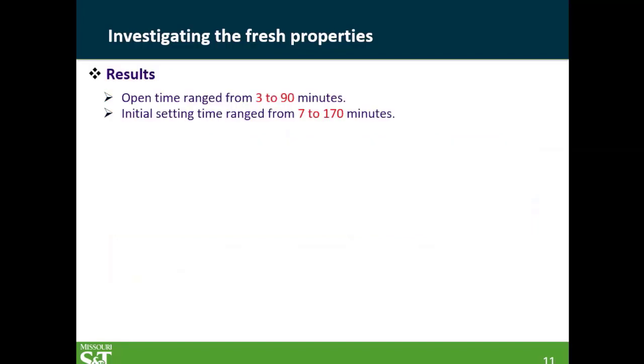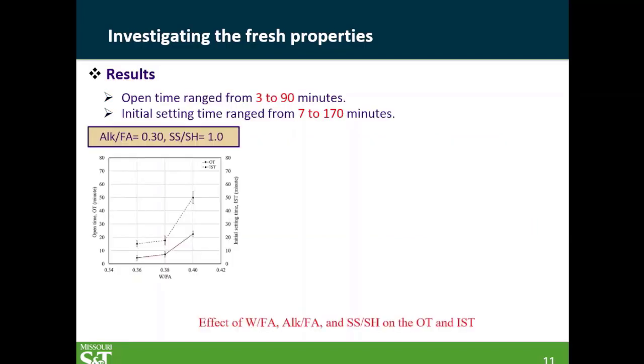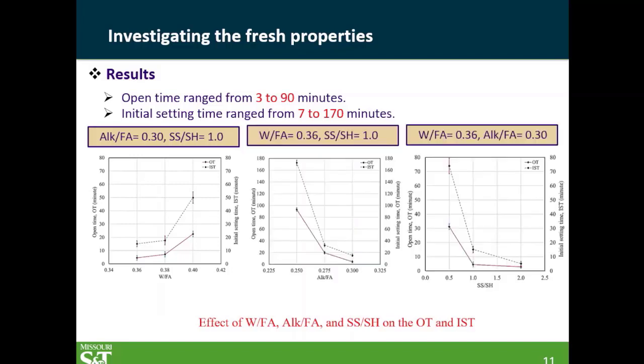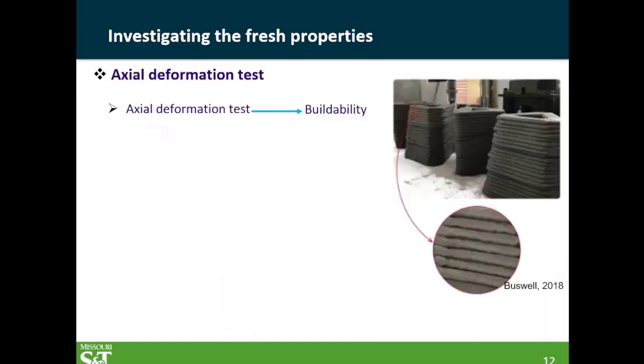And then we also ran the initial setting time, and then we have some relationships over here. So for example, as we would expect, by increasing the sodium silicate to sodium hydroxide ratio, you would see a drop in the open time and also the initial setting time. For the different mixtures that we selected, we have open time ranging from 3 minutes to 90 minutes. This is slightly lower than the initial setting time, from 7 minutes to 170 minutes. The other property that we looked at is the